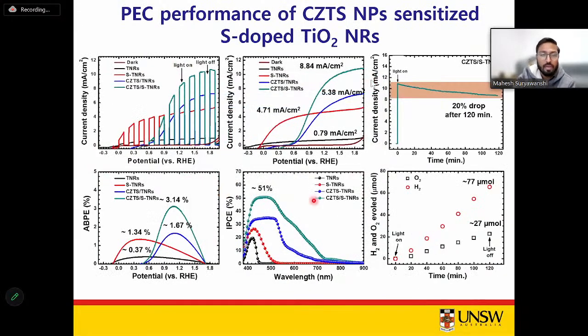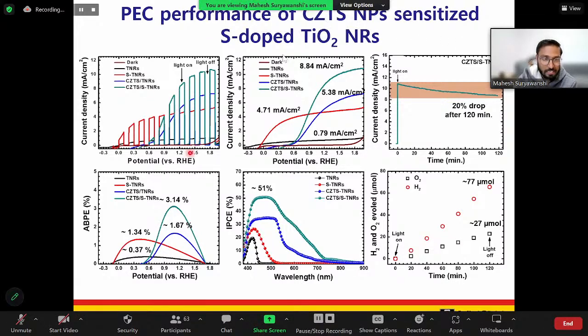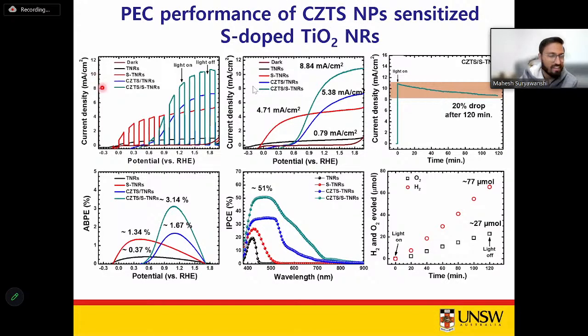So once we have done those, we tested the performance of this whole system for the water splitting reaction. Though TiO2 gives us a decent photoelectric current density, it is relatively low compared to all other samples. But interestingly, when you sensitize the CZTS nanoparticles on sulfur-doped TiO2 nanorods, the current density is very, very high, about 10 milliampere per centimeter square.